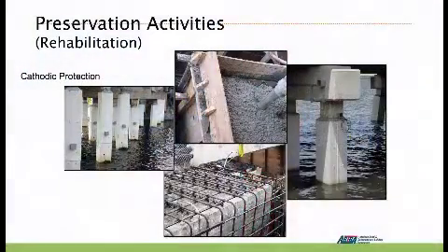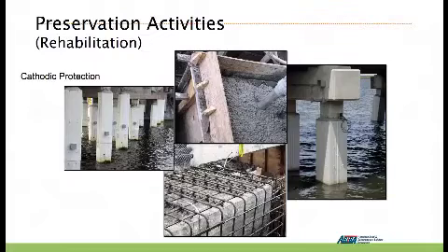So there are other options available to extend this life and prevent any further corrosion. Those are called cathodic protection. If the salt is not up to the steel level, you can remove it and put an overlay on it. Overlays are a very good way of rehabbing a deck, but on the substructure or in the marine environment, the salt is always there. So the only way you can really extend the service life and preserve your structure is by using what's called cathodic protection.